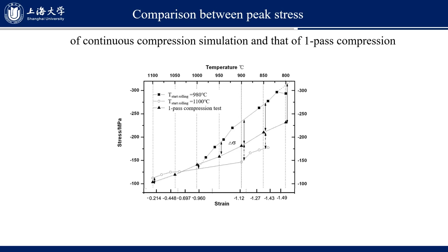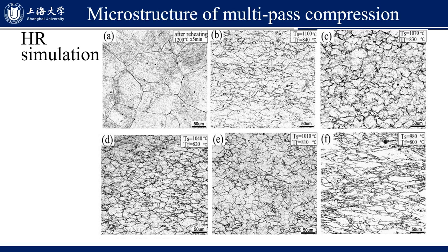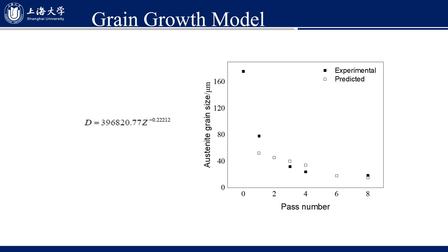The hot rolling simulation shows the microstructure changes a lot at the first several steps. And for the deformation temperature set very low, as the start deformation temperature of 980 degrees C, the microstructure shows elongated austenite, say not fully recrystallized. This is the grain growth model for the multi-pass deformation condition. Grain size changes with the Zener-Hollomon parameter.